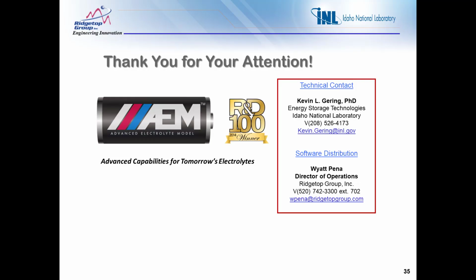Well, additives, in the conventional use of that term, are used to enhance the passivation process of the electrode. So the solid-electrolyte interphases that are formed on both the cathode and anode early in a cell's life are very much dependent upon the choice of electrolyte and the additives. The AEM allows those additives to be input at the kinds of quantities that you would expect, generally between 1% and 5%. And so you get a true rendering of their impact on the electrolyte properties.